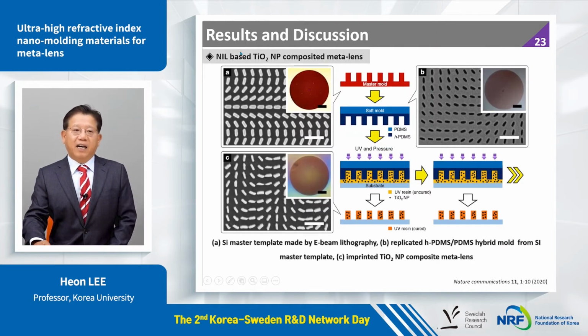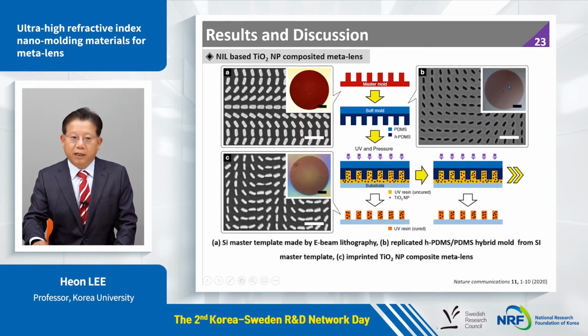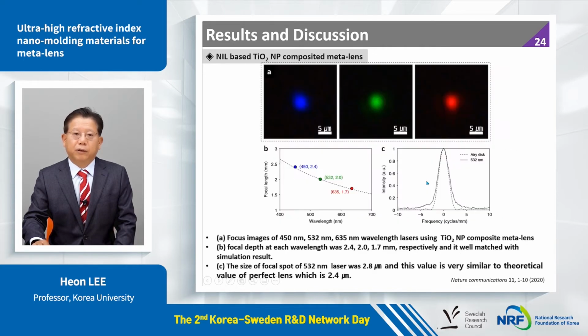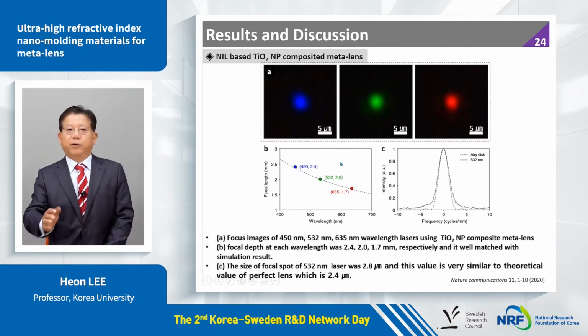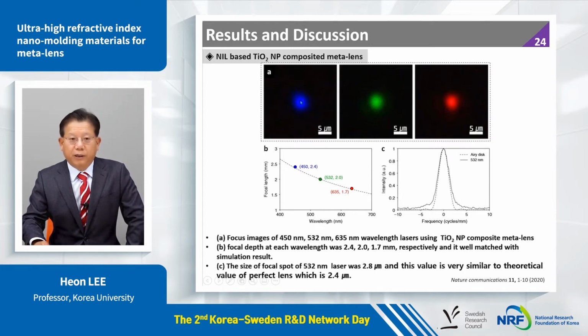And another thing is the metalens, not the hologram type. This is the master template, replica, and imprinted metalens. The same process was used, and I measured the performance of the metalens. With 450, 532, and 635 nanometer wavelength lasers, the metalens has focal depths of 2.4, 2.0, and 1.7 millimeters. This is the focused image, so you can simply see the focus size. It's very small. In the 532 nanometer case, the focal spot size was 2.8 micrometers, and that value is very similar to the theoretical value of a perfect lens, which is 2.4 microns.